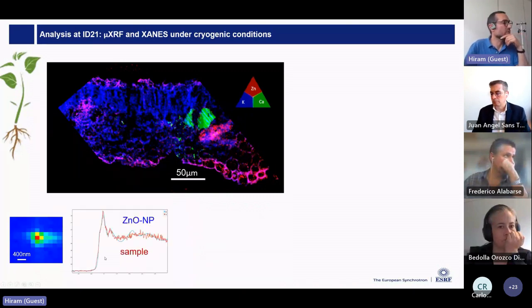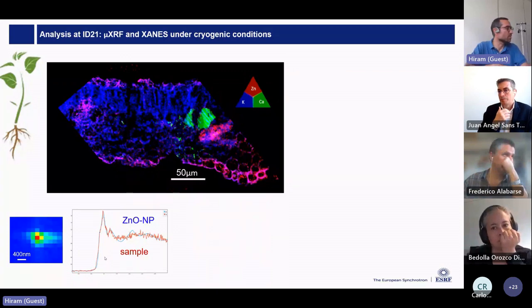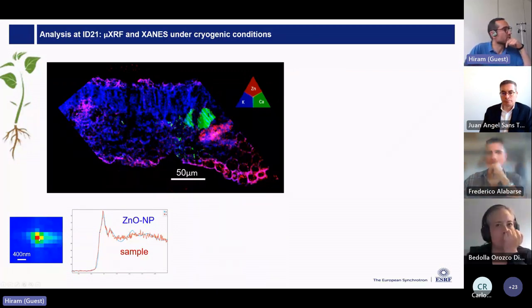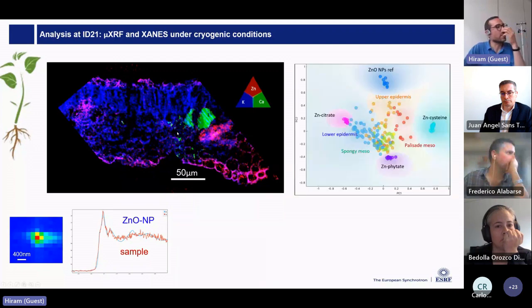And Hema mentioned the new generation of double crystal monochromator at ESRF. We are lucky we got the first one, the prototype. So we came with some difficulties, but we are now using it, and we can perform nanospectroscopy. We can really do the XANES on the hotspots where there's still signal of the zinc oxide nanoparticles. But more importantly, because we go so fast, we can scan in many points all around the tissue, and then we can classify them and compare them to references.